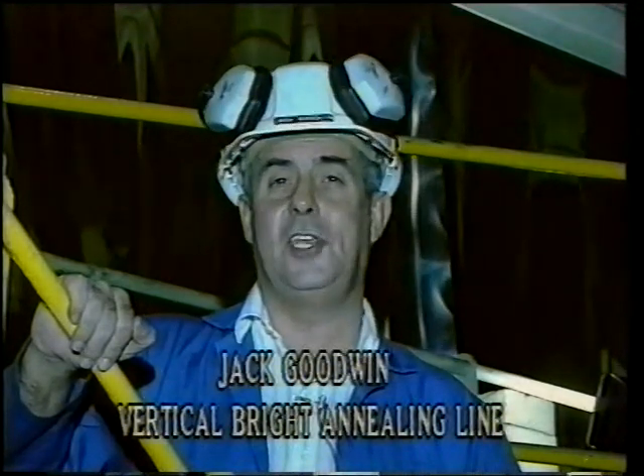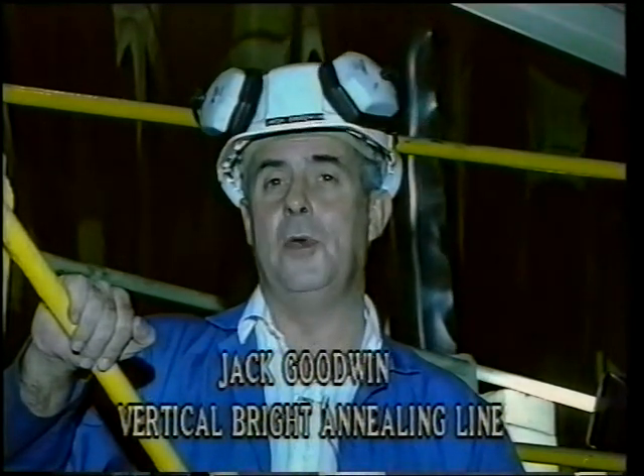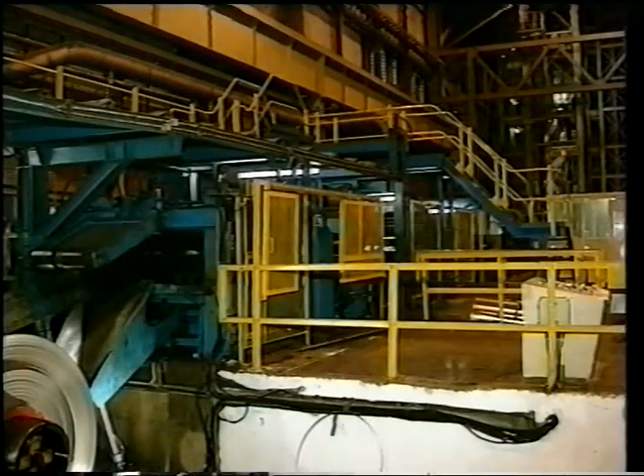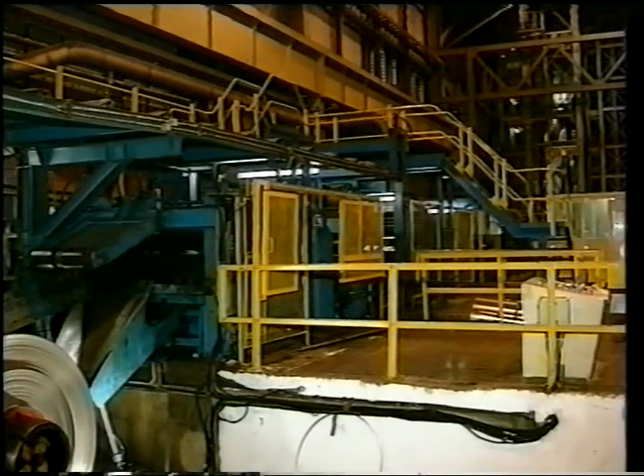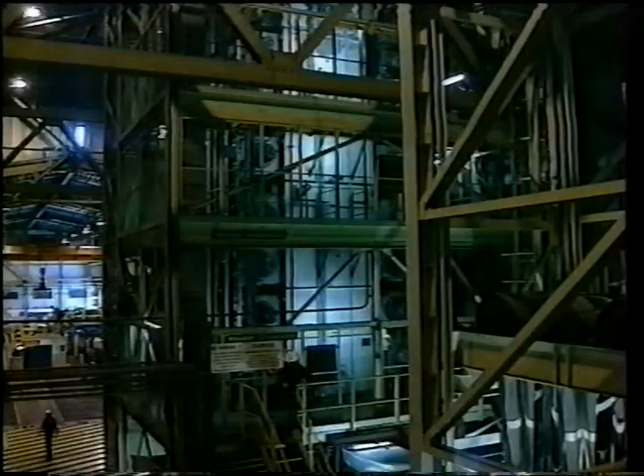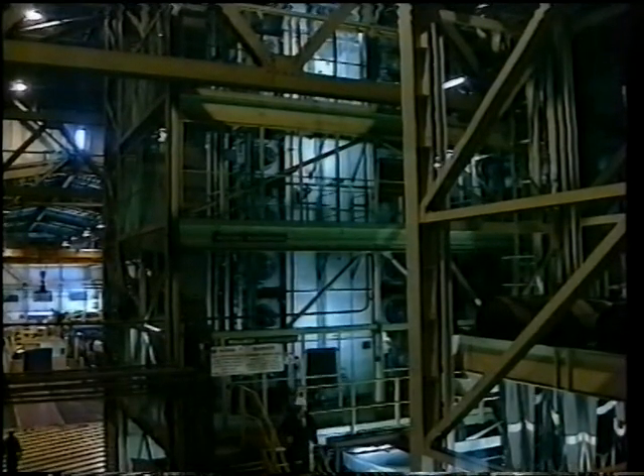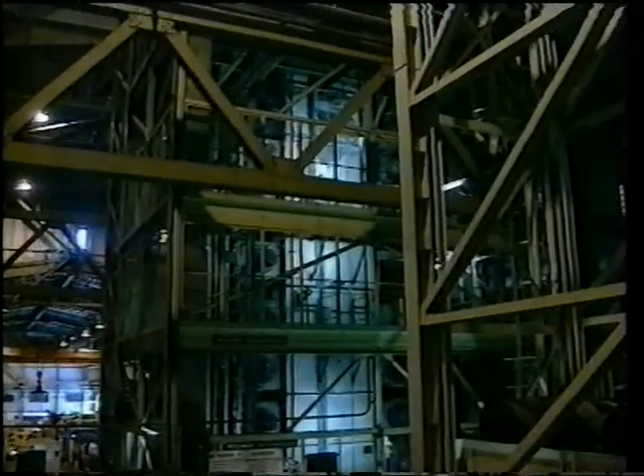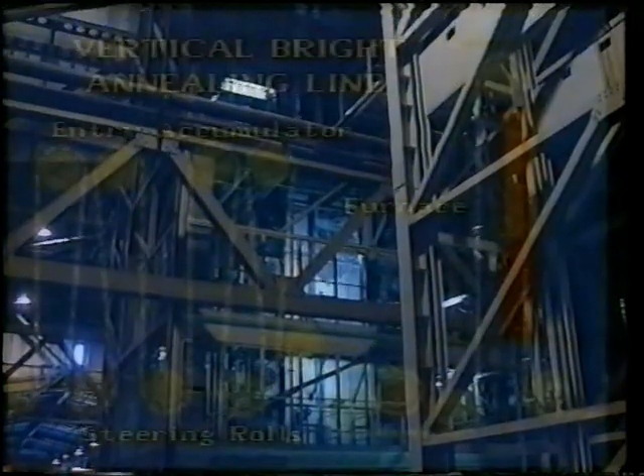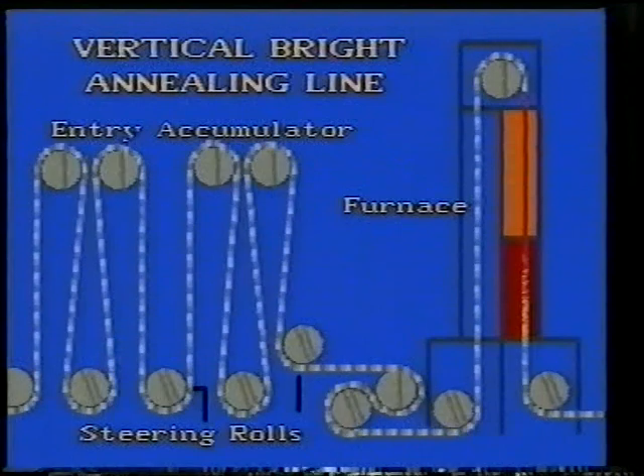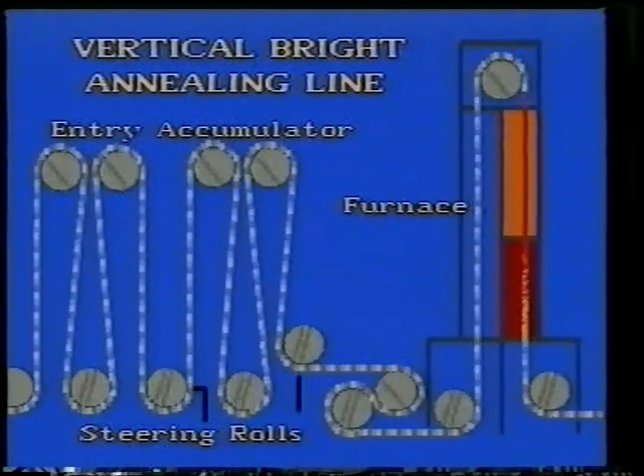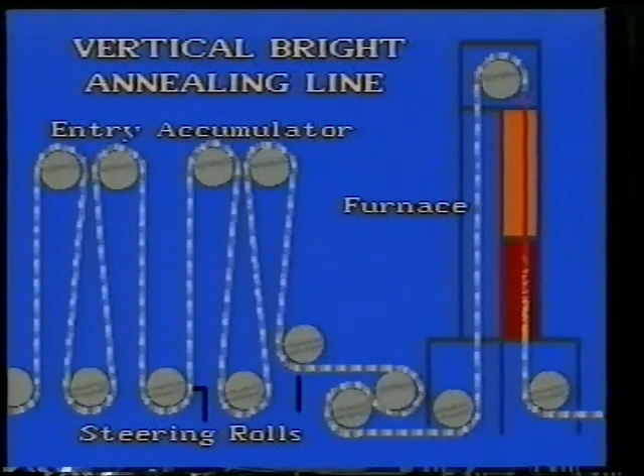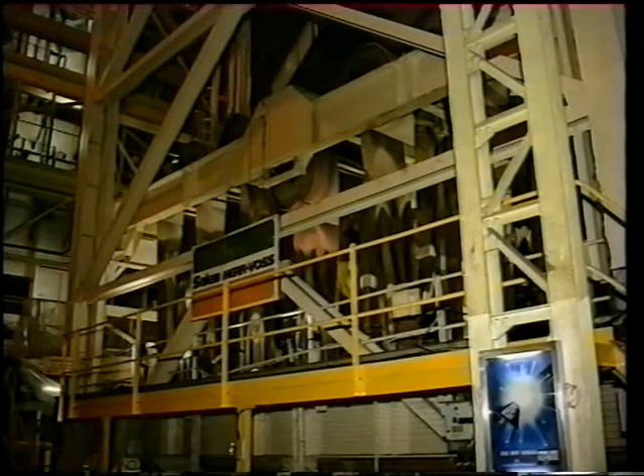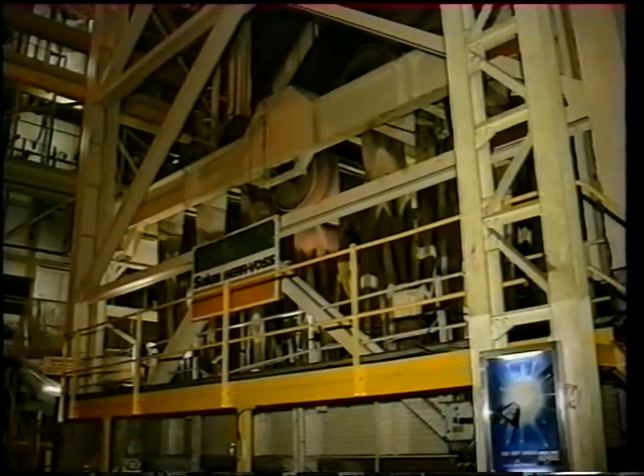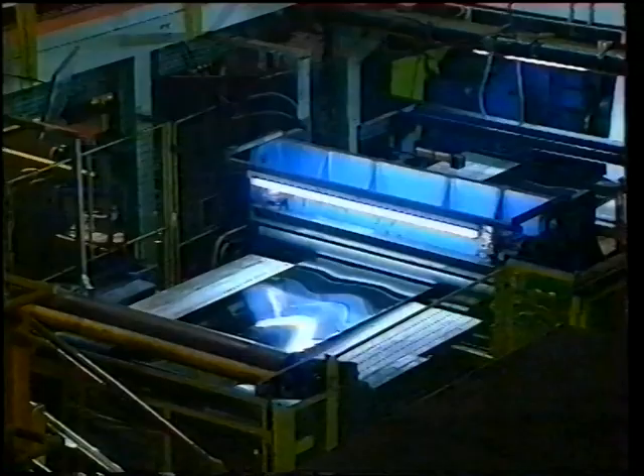20% of the material produced is destined for bright anneal finish and is softened here on the bright annealing line. After being degreased and dried, removing all the rolling oil, the strip is heat treated in a vertical electrically heated furnace. This furnace has an inert atmosphere of nitrogen, carefully controlled to inhibit the presence of oxygen, which would cause oxidation of the strip surface during the annealing process. After cooling, the strip once more passes through a further accumulator, is inspected, sheared and recoiled.